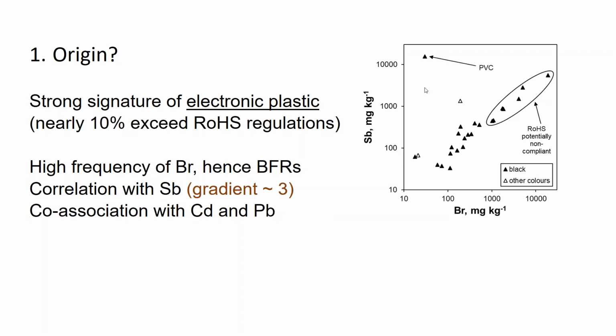And we find here, and in the previous example, nearly 10% of our beach plastic exceeds those RoHS regulations on electronic waste. So we have a high frequency of bromine in these plastics, hence flame retardants, although we haven't been able to determine which type of flame retardants they are. And they are also co-associated with cadmium and lead. So we tend to get a lot of bromine, quite a lot of antimony, but we also find cadmium and lead there. So where does the cadmium and lead come from then?